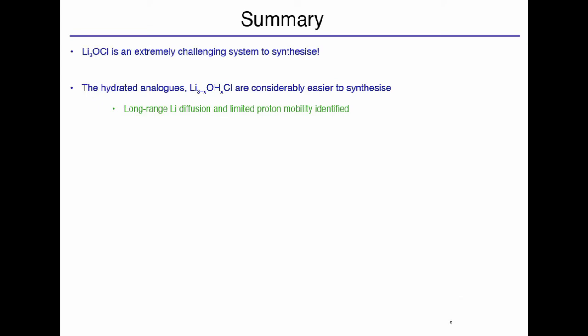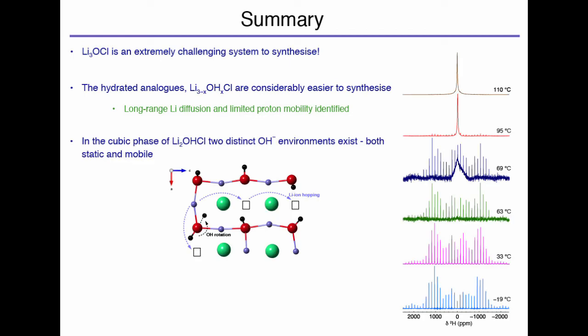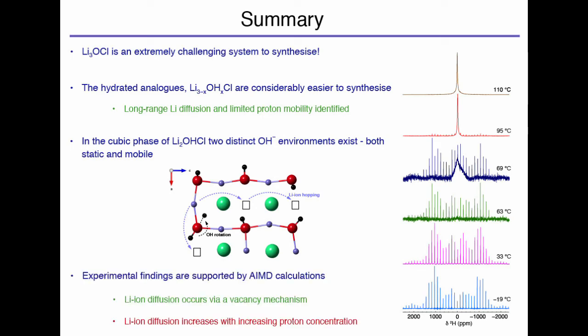Okay, so for this part of the talk, hopefully I've shown you that these anti-perovskites are quite a challenging set of systems to study, and they're really, really difficult to synthesize. So far, we've had basically no success with the synthesis of those. But we have managed to synthesize the hydrated analogs, much, much easier to make. And we've shown within our experiments that they have long-range lithium-ion diffusion and limited proton mobility. In the cubic phase, we think that we've identified two distinct environments, static OH groups and locally mobile OH groups, and we've identified this potential mechanism for how these things work. Our experimental findings have been supported by our molecular dynamics calculations. So we think that lithium ion diffusion occurs via this vacancy mechanism, and lithium ion diffusion increases with increasing proton concentration. So the more you can manipulate this to get the higher ionic conductivities, the better.